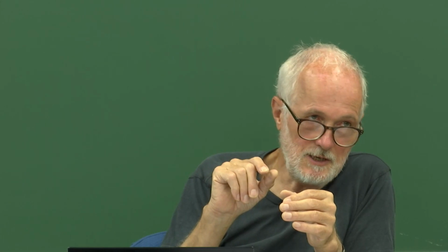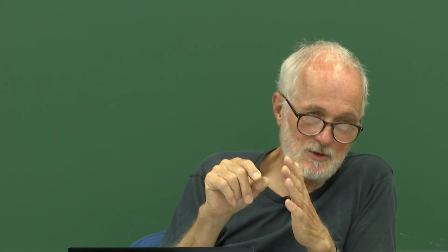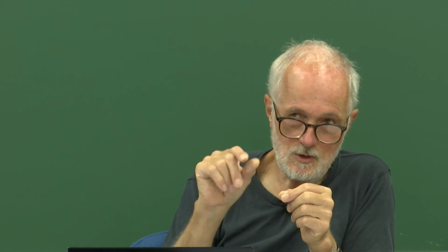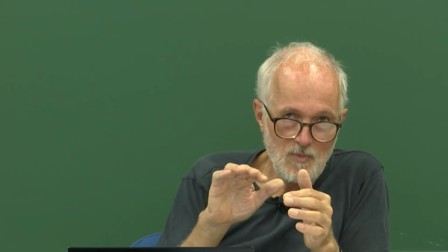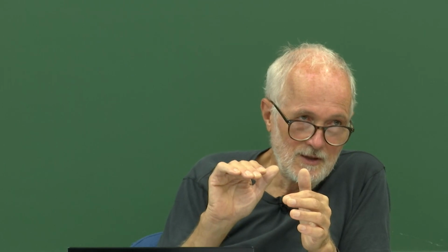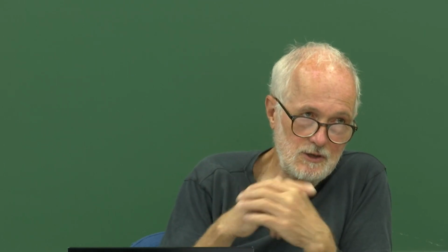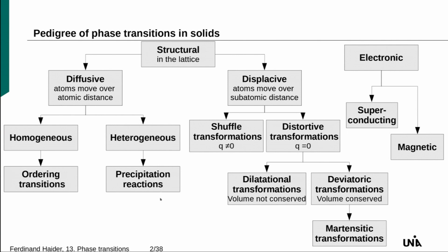Or another example is copper zinc, brass, beta brass, at 50%. In the ordered structure, the zinc atoms occupy the corner sites, and the copper atoms occupy the body-centered sites. Above, I think it's again around 400-something, this superstructure disappears, and the copper and zinc atoms are equally distributed. This can be measured, for example, by electrical resistivity - you see a clear change in electrical resistivity, and other properties also change. So these are the ordering transitions and the precipitation reactions. I call it here 'reaction' - normally we don't speak of transitions or transformations here, but it is a phase transformation.